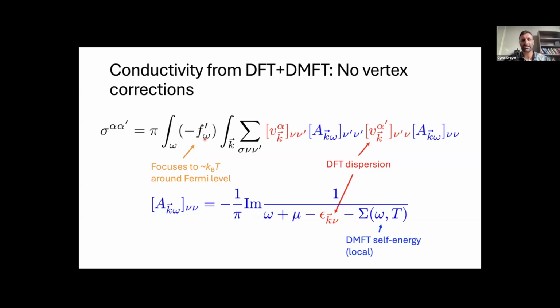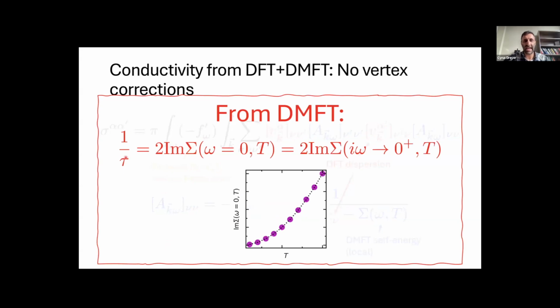So we have here, of course, a derivative of the Fermi function with respect to energy. And so if we're interested in the low temperature transport, then basically this focuses us in around a very small region around the Fermi level. So we could define a scattering rate as actually the imaginary part of the self-energy just evaluated at exactly frequency equal to 0. Or if we're on imaginary frequency, extrapolated to imaginary frequency equals 0. And then in the Fermi-Liquid regime, we should see that the scattering rate has a quadratic dependence with temperature.